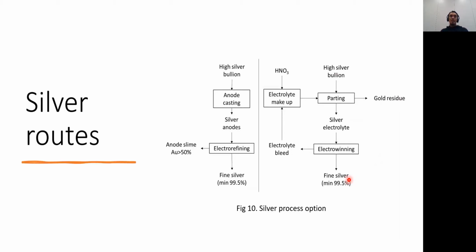Because for example, if they can refine gold in 3 days, and they need to return this gold to the mining companies in 7 days, they have 4 days of window which they can use for bullion trading, investment trading, this kind of thing. So it's a huge advantage. If they can choose, they will choose the gold route first. But for high silver bullion, they cannot really do that. So unfortunately, it will need to go to silver routes.